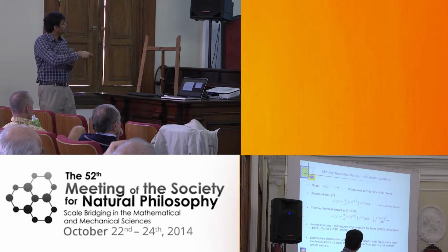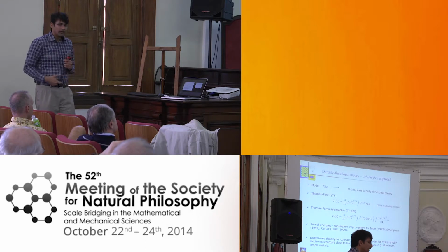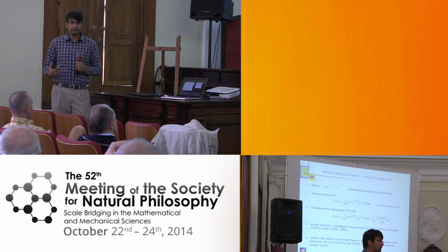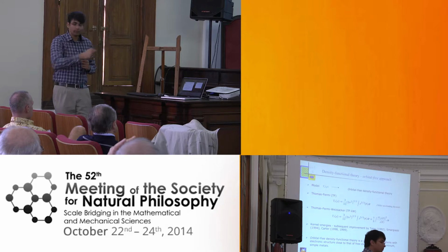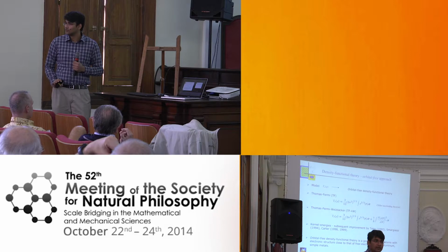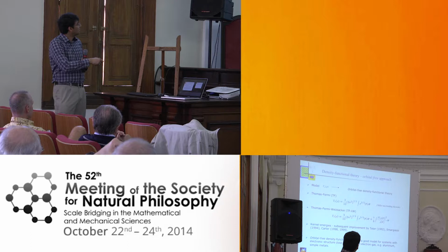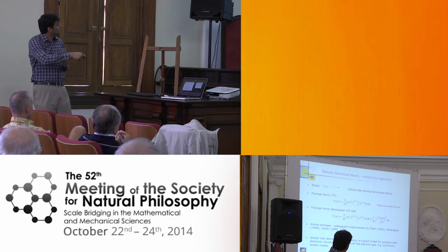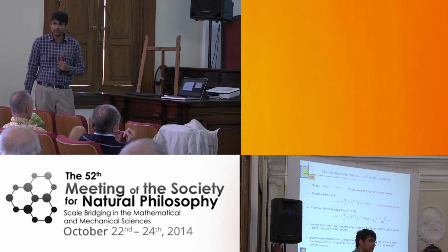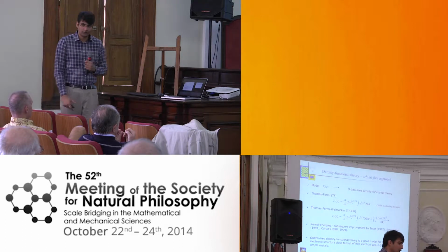But the downside of this Thomas-Fermi kinetic energy functional is that Teller showed that this is good for single atoms, but when you have multiple atoms, this particular form of the kinetic energy functional doesn't predict binding in materials at all. So for materials science, it is practically not useful. Then von Weizsäcker added a correction term, which is a gradient term, which fixed this non-binding in materials, and that results in what is called the Thomas-Fermi-von Weizsäcker family of kinetic energy functionals.